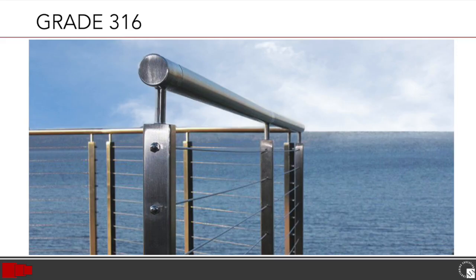For commercial railings with a higher resistance to corrosion, look for 316 grade stainless steel railings. The material's chromium content interacts with the air to basically repair and protect itself from scratches and rust. If your commercial railings will be used in industrial applications or outside, 316 grade steel is likely your best choice. It works well in more extreme environments due to the high corrosive resistance. Although the 316 grade has a higher corrosion performance than grade 304, you should always consult with your manufacturer when using stainless steel in high salt or coastal areas to fully understand the level of corrosion resistance and expected performance for the specified stainless steel grade.